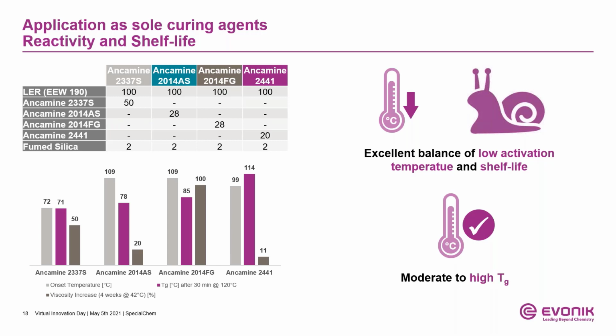Ancamine 2337S clearly shows the lowest onset temperature of all products shown here, with around 70 centigrade, but also the lowest thermal stability in terms of the glass transition temperature after standard curing. In case higher thermal stability is required and also onset temperatures around 100 centigrade are feasible, Ancamine 2441 is an excellent choice, whereby it also offers the best shelf life stability of all products shown here.